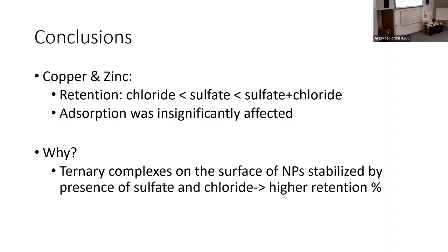And why? So we suspect that the ternary complexes on the surface of these nanoparticles are stabilized by the presence of sulfate and chloride, which causes a higher retention rate because these nanoparticles are more tightly grasped onto the metals, which makes them harder to take off when we desorb them.